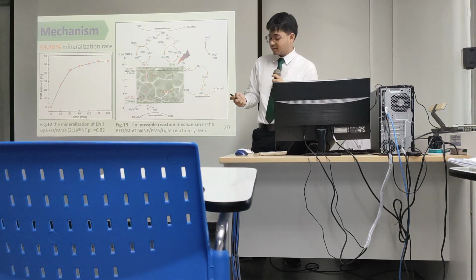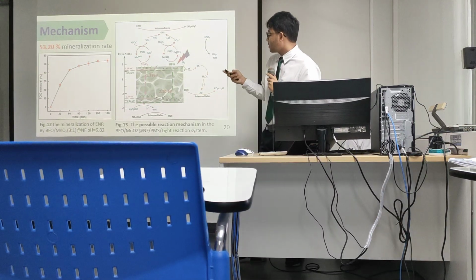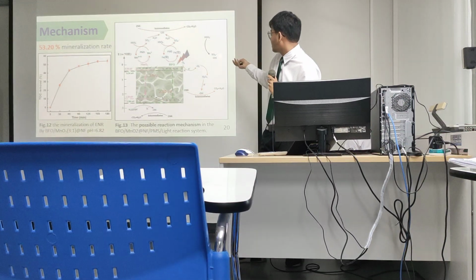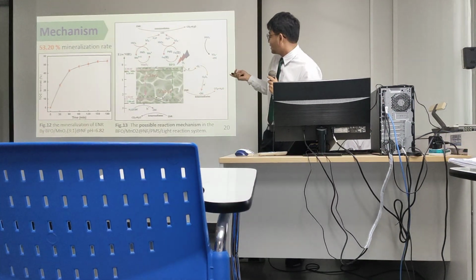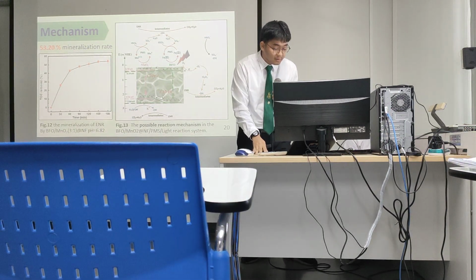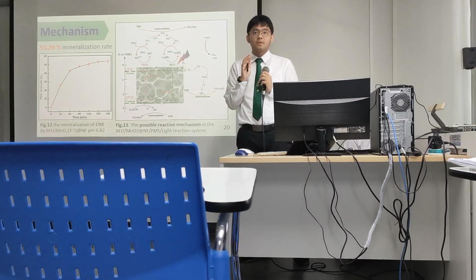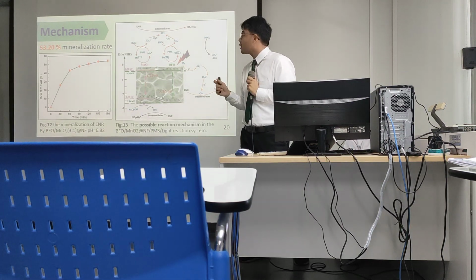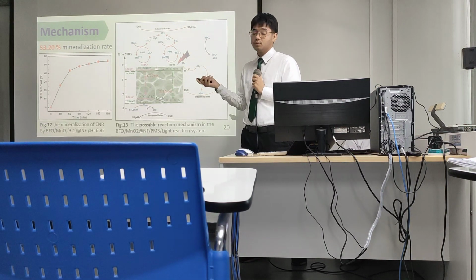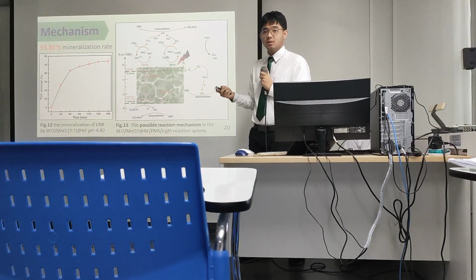This is the mechanism of reactions. You can see there are many reactions that produce hydroxyl radical, but there is only one here, which is the superoxide radical. As I told you, enrofloxacin can be reduced by 87.5%, but total organic carbon decreased by only 53.2%. It's because the intermediates are left in the solution and are still degrading.